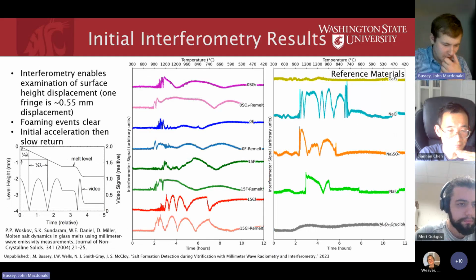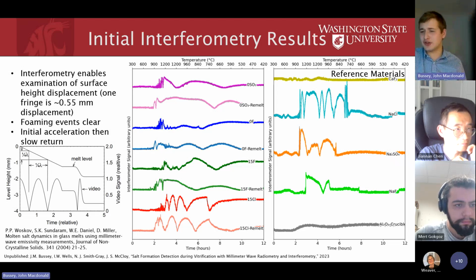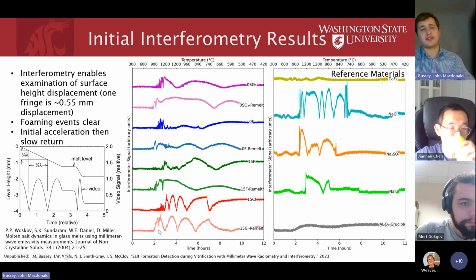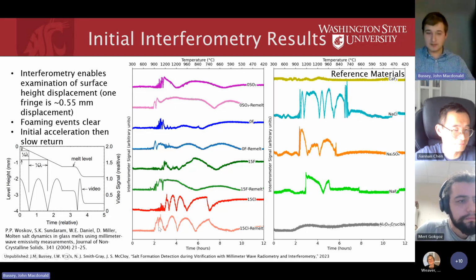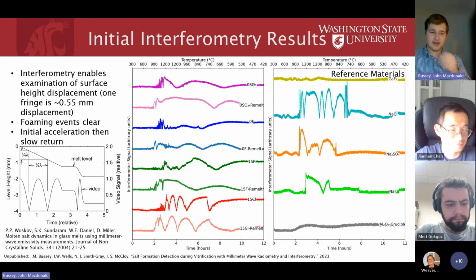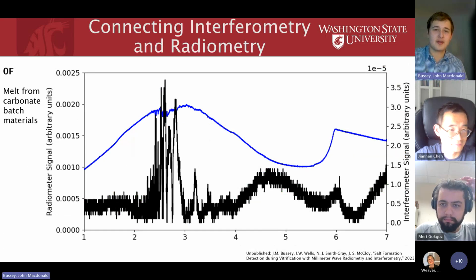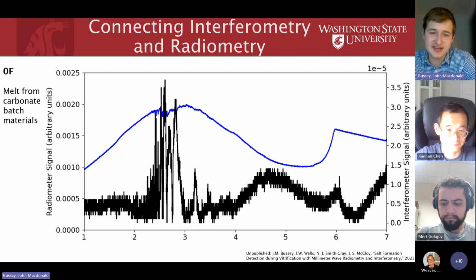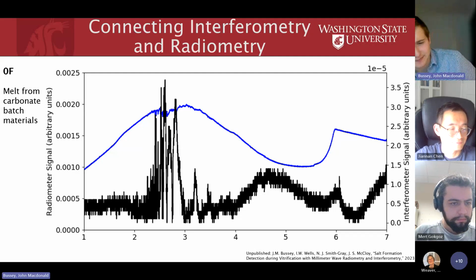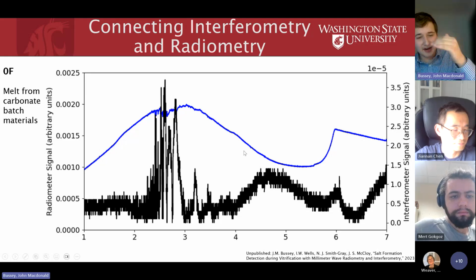We also get data out of this instrument called interferometry, and from that we're able to look at the surface height changes. The main feature here is at around 2.5 hours, which is when we reach our top temperature, we see these large spikes, and each of these humps is related to the cosine curve. Each single period of one of these is a quarter of a wavelength, so about 0.5 millimeter of surface height change. And so we were able to connect that with our radiometry and see that that's exactly when the off-gas is happening. Another interesting thing to see is right about at the end of when this is happening, and when the radiometry starts to decrease.